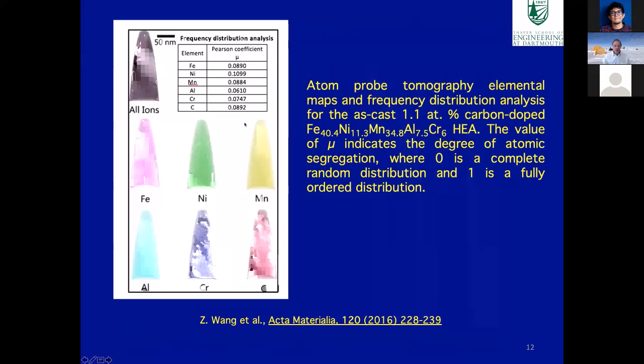And this is the sort of result we've got. This shows the different atoms in the microstructure, and this Pearson coefficient up here shows you whether the alloy is random or not. If the Pearson coefficient is close to 0, then you've got a pretty random alloy. And you can see that indeed is the case: we've got pretty much a random solid solution of the material.